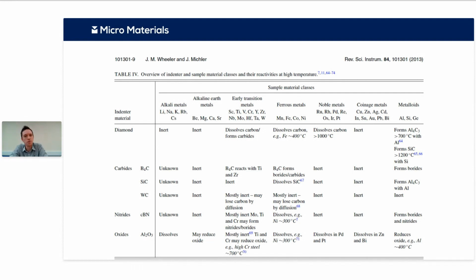For example, we have found that performing tests on nickel with a sapphire indenter, an aluminium oxide indenter, is okay. So it says here that it may react, but we've done several tests at very high temperatures on nickel with sapphire, and we don't see any degradation of the indenter. But nonetheless, this still provides a good guide to work out which indenter is probably the best choice for your material.